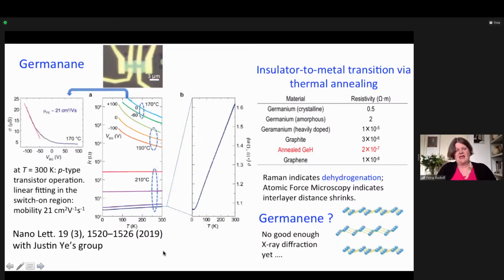What is extremely interesting is what happens if you heat this material in a device configuration. That was done with my other colleague Justin Ye, who is also at the Zernike Institute. He made another type of device structure also with our material, and then he started heating. And what you find is that you lose hydrogen and you get a new form that only contains germanium, but germanium can have many different structures. We think it is germanene that we get, because the Raman indicates it. The conductivity is certainly a metallic conductivity.